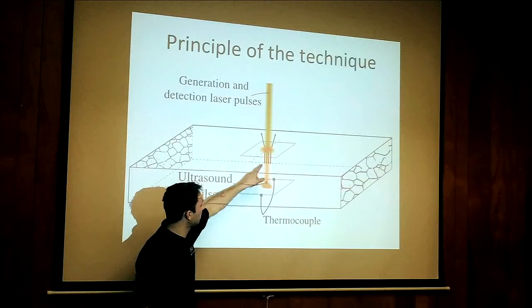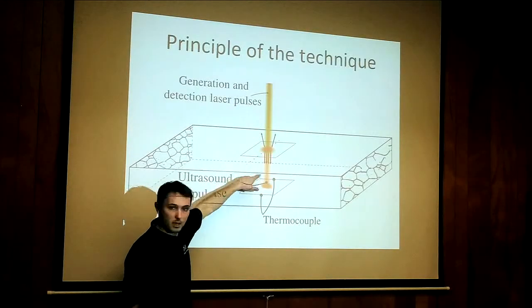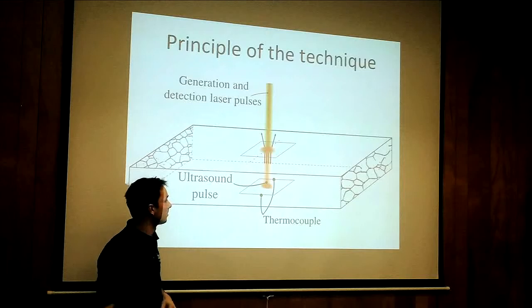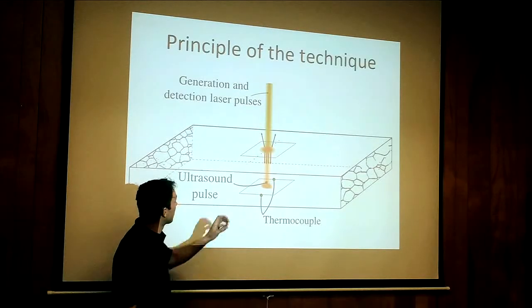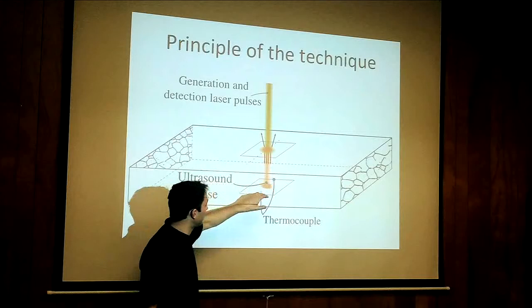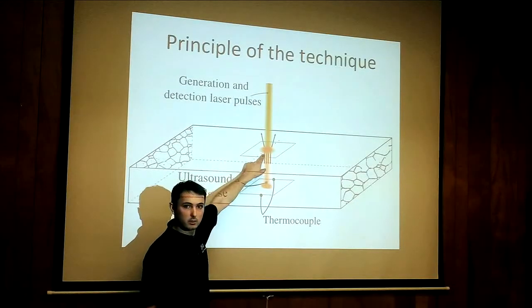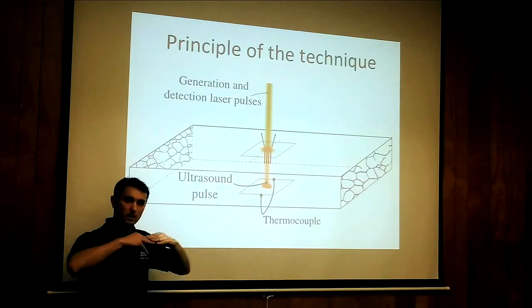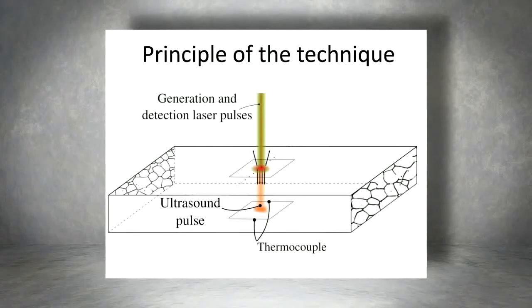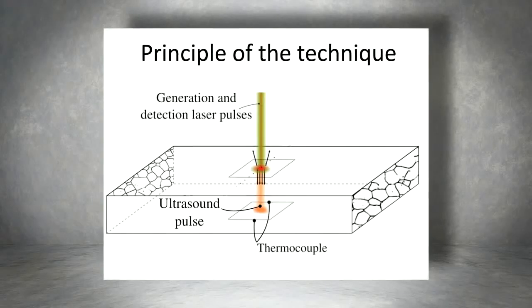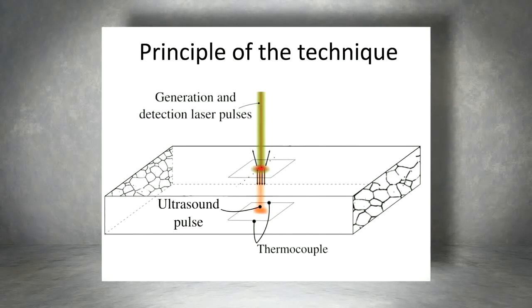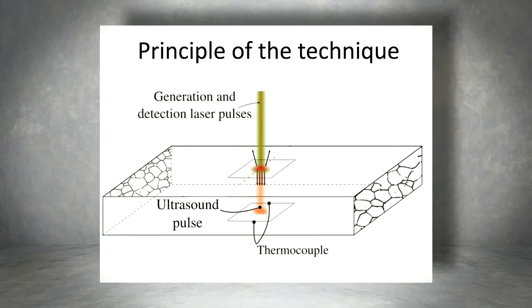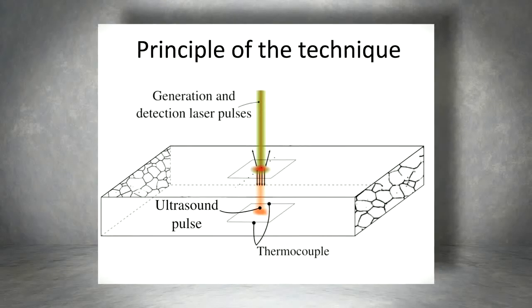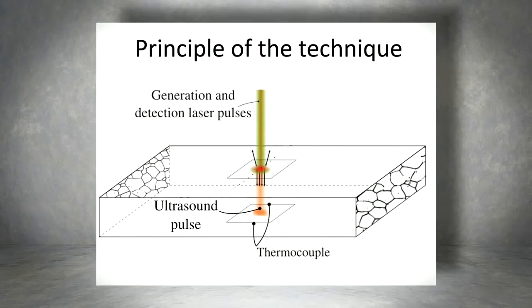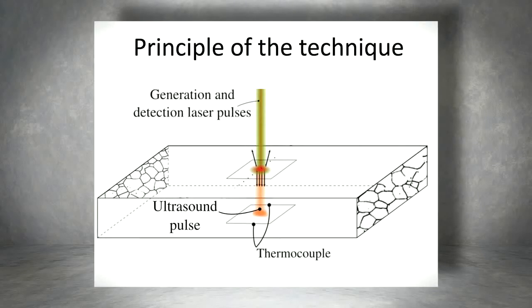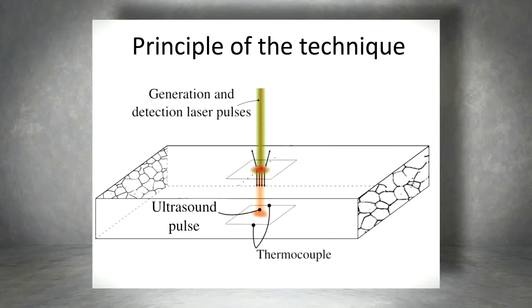This pressure wave, represented in red, is going to bounce back and forth between the two surfaces of the sample. And there is a second laser which is looking at the sample, and each time this wave comes back at this generation surface, there will be a tiny microscopic displacement that will polarize the light of this detection laser. This light reflected on the sample is collected in the probe, and thanks to an interferometer, we can access a signal which is proportional to the surface displacement measured here at the generation surface.